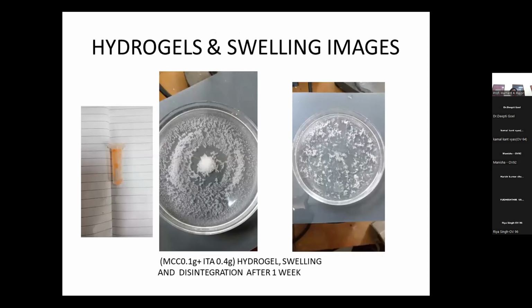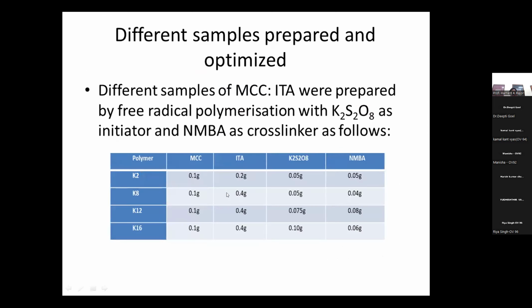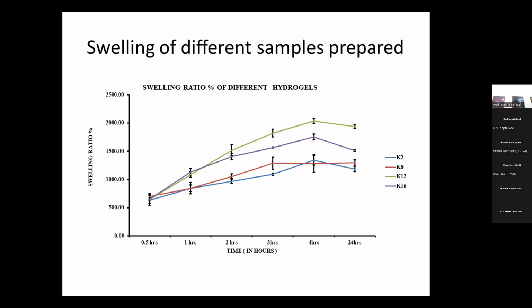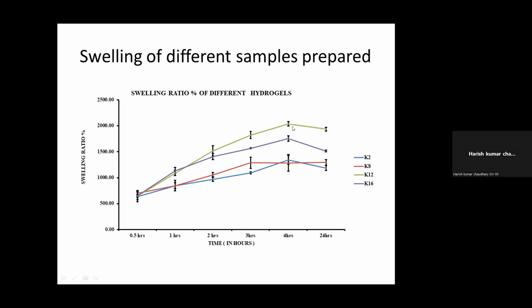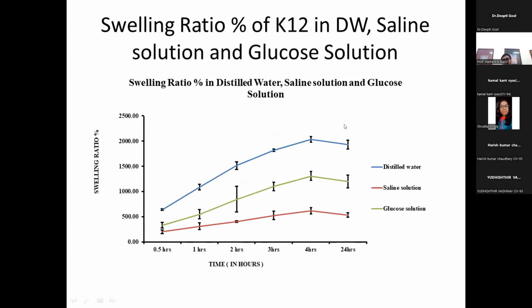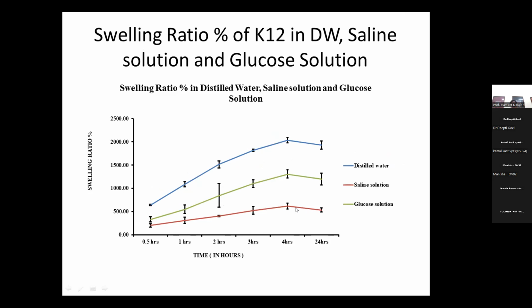These are the cellulose hydrogels that were obtained, and they were optimized with different amounts of cross-linker and initiator. They were made by free radical polymerization. Coming to the samples that I prepared, the K12 sample shows the best swelling ratio, and later these ratios were calculated in distilled water, saline solution, and glucose. It shows that swelling is lower in the saline solution, greater in the glucose, and highest in distilled water.